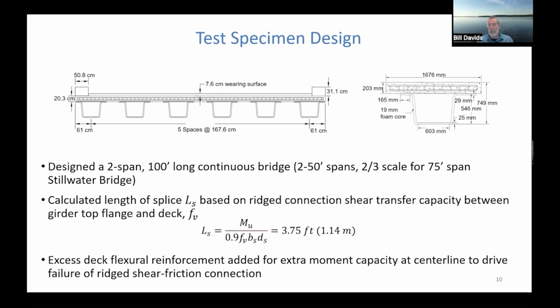And you can see we calculated a length of 3.75 feet. That is, I think, 7.5% of the 50-foot span. So it's not a large length that we infill. It's actually pretty short. We also added excess deck flexural reinforcement. So we've got to have tension steel in the deck to carry that negative moment across that pier. We added a little extra for extra moment capacity to try to drive the failure to occur at that ridged shear friction connection. And as you'll see, we were partially successful with that, and in a good way.